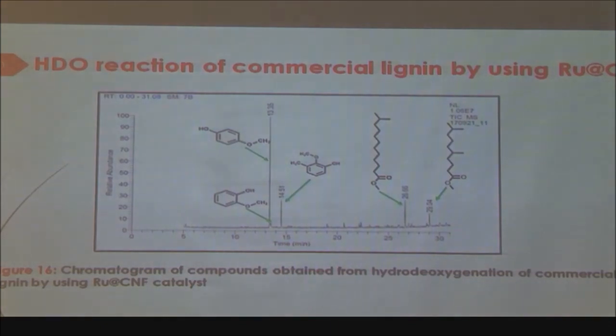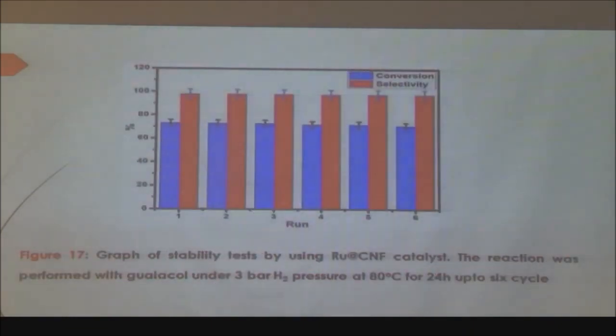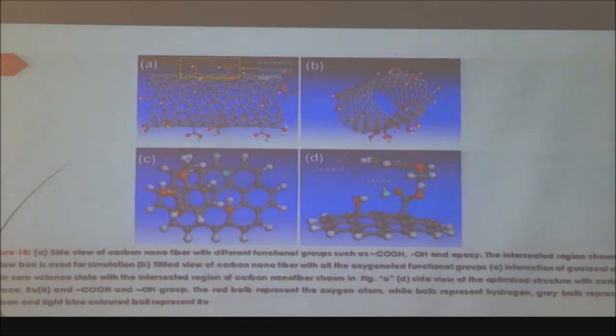So this is the HPLC graph, where we have shown the peaks of these compounds that we obtained and compared their mass spectra. So this is the recyclability of the catalyst. Again, we tested it up to 6 catalytic cycles. And there was still a question, whether the ionic or radical mechanism was prevailing. So we did one more attempt.